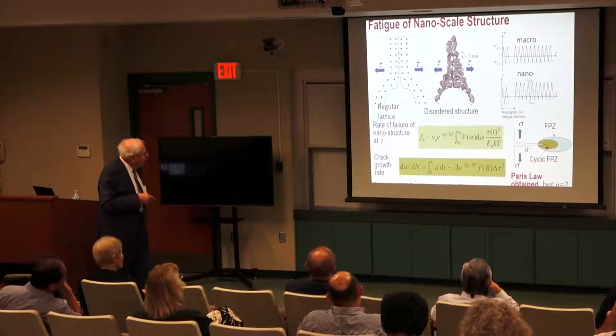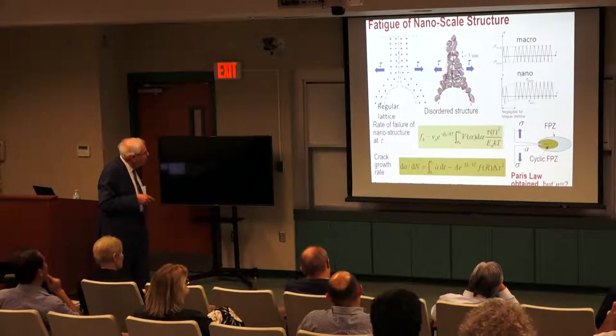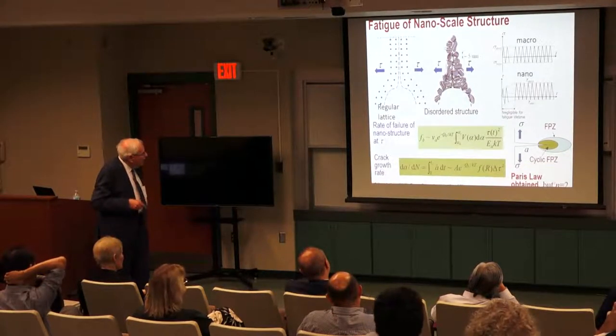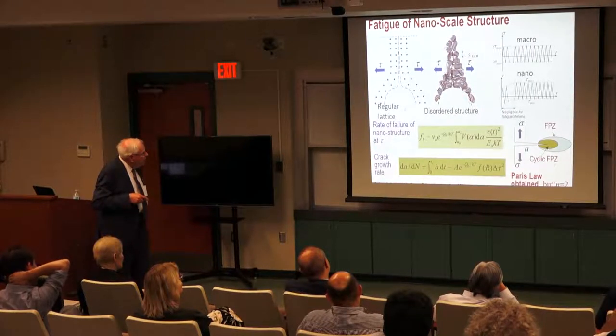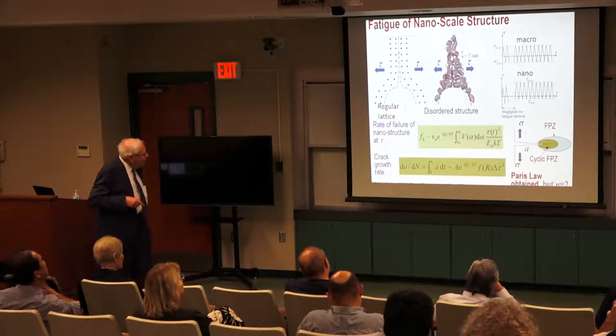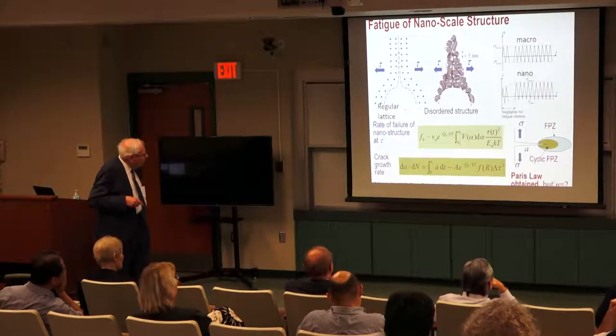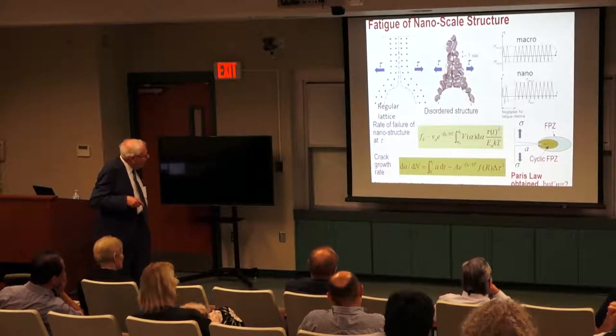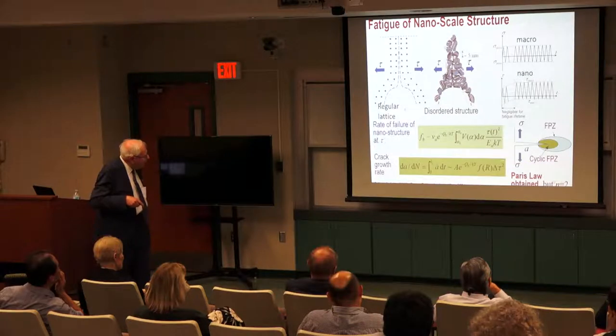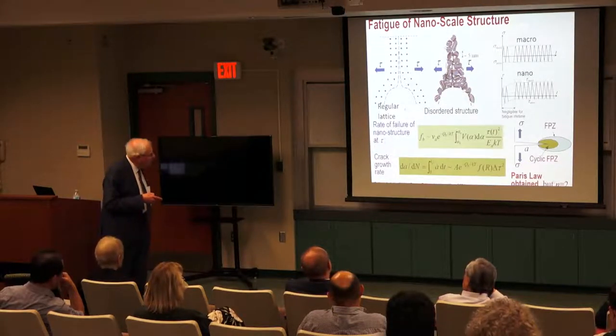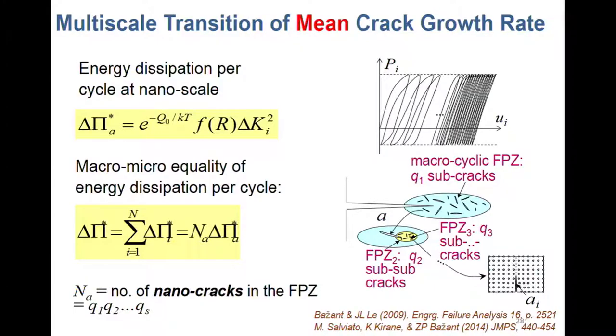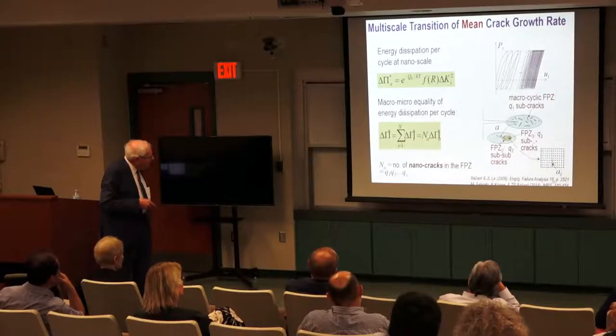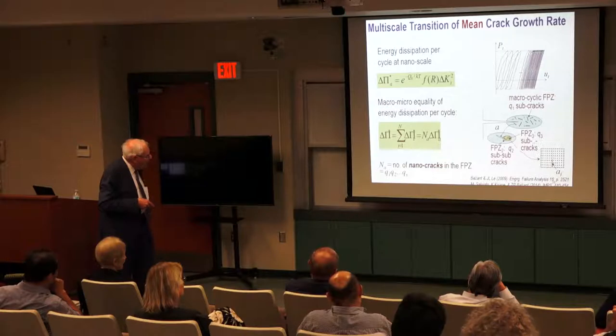So you can again imagine in concrete it looks like this. There are nanoscale particles, but no order as in crystal material. You need to integrate it over a cycle, and you obtain a law by the integration that the advance of the crack is again proportional to a power of the imposed stress. Now, what has to be noted here is that all these cracks at one scale have subcracks on a smaller scale that have subcracks until you go to nanoscale.